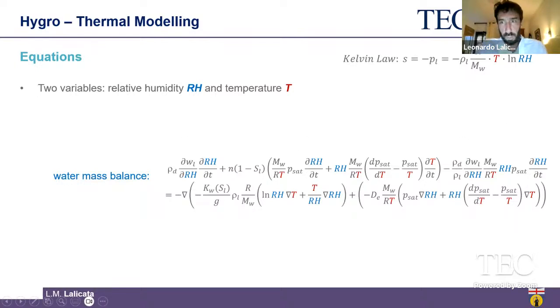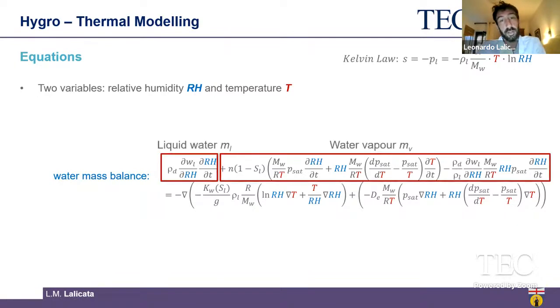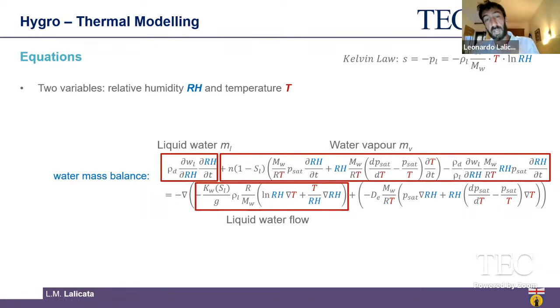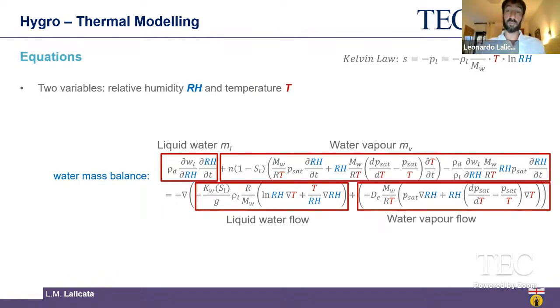That is this awful equation, which is made of a number of terms. But basically, what it's saying here is that we have a storage term for the liquid water plus another storage term for the water vapor mass. That must be equal to the fluxes, the liquid water flow that follows the generalized Darcy law for the liquid flows, and the water vapor flows that obey the Fick law. So this is a diffusion process through the medium.